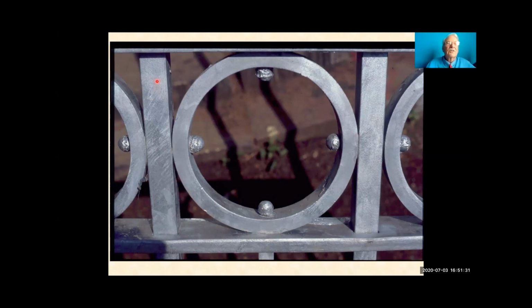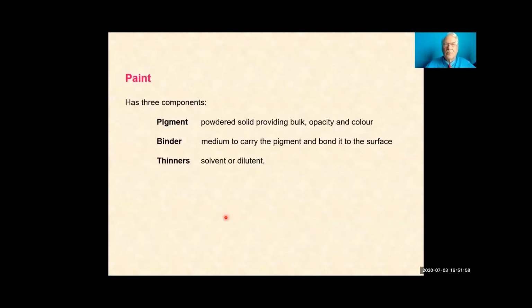It's uneven, it's thinner at the top than it is at the bottom. And it's absolutely not recommended for historic metalwork, particularly castings. You mustn't zinc galvanize castings because of that porosity. I'm afraid the caustic dip goes into the porosity and it will very soon corrode underneath the zinc coating. So not preferred for historic metalwork. That's why we have to use paint.